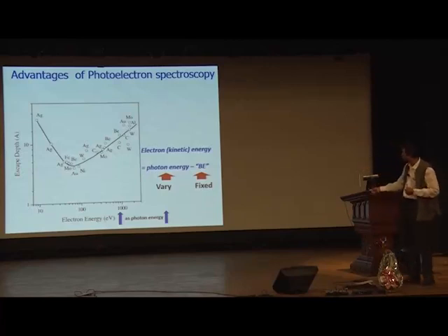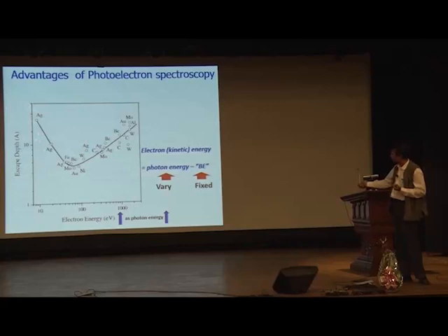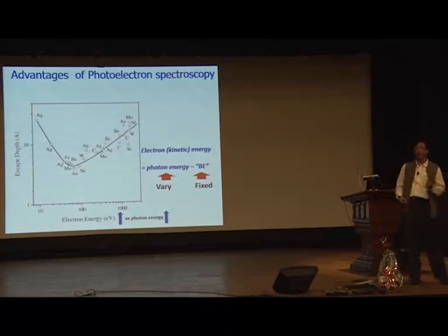And that's a quantity which we call the escape depth, plotted over here. It happens to be a very sensitive function of the electron kinetic energy. And it has this particular shape: from small kinetic energies, it starts with a large value, goes down and comes up, and then again becomes large. You may think it's a bit peculiar, but it's very easy to understand why it should happen, because you can imagine the limiting value of zero kinetic energy.